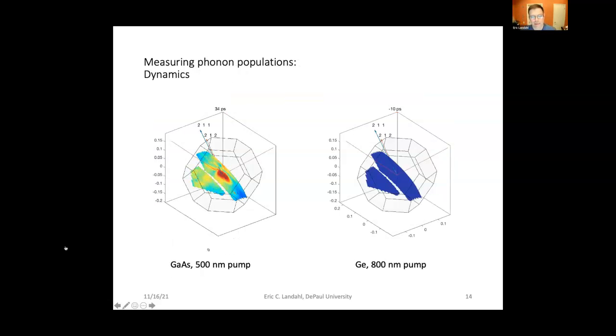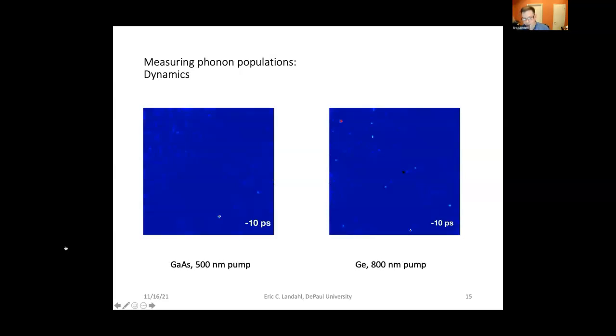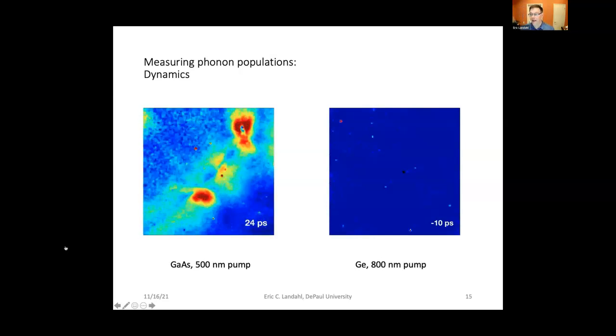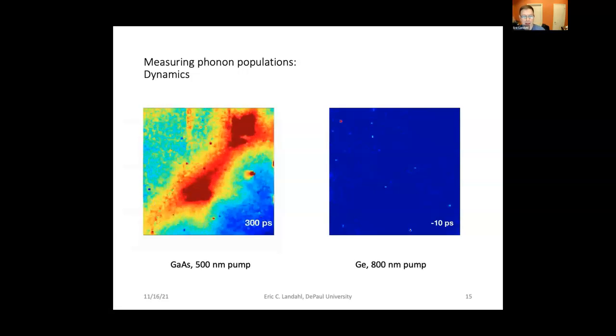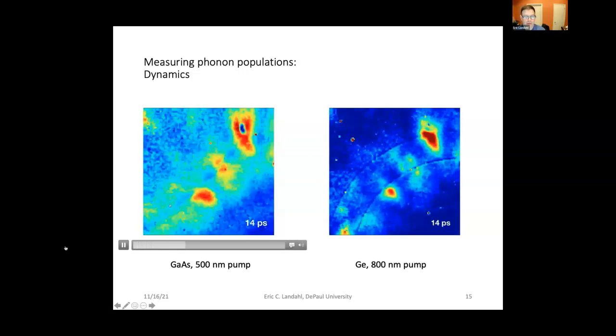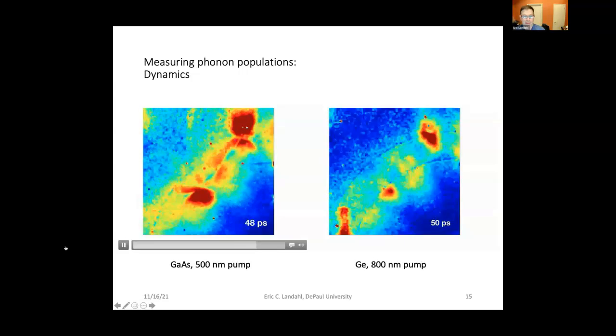When we look at the full dynamics, I'll show these videos in a couple different formats. Here it is with the 2 adjacent Brillouin zones stacked on top of each other. For both gallium arsenide at a 500 nanometer pump, which is sufficient to go into many valleys, as well as the 800 nanometer pump for germanium, which gives a similar range of signals. A lot of interesting characteristics become apparent, particularly at the edge between the 2 zones, as you can, for instance, see right here. This is just a raw data view of the subtracted images from the top. So the first Brillouin zone centered around this brightest dot here, and the second one over there.